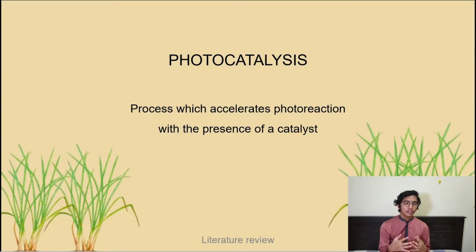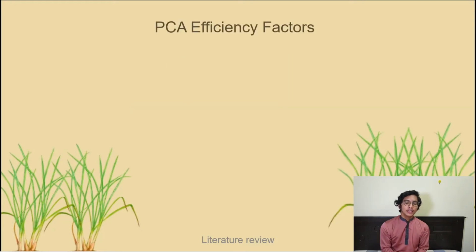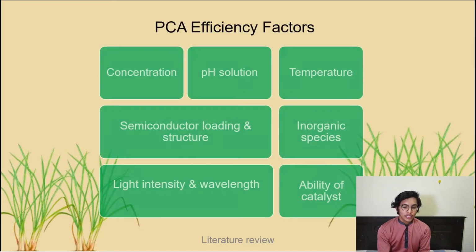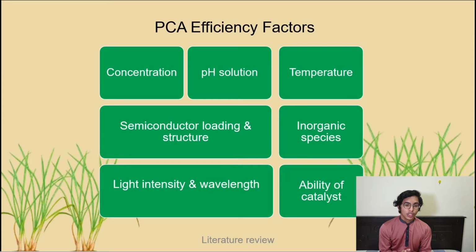In our case, the catalyst being semiconductor. The efficiency of photocatalytic activity depends on several factors, which are concentration, pH solution, temperature, semiconductor loading and structure, inorganic species presence, light intensity and wavelength, and the ability of the catalyst to produce electron-hole pairs.